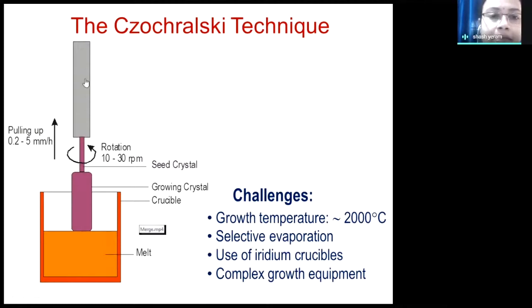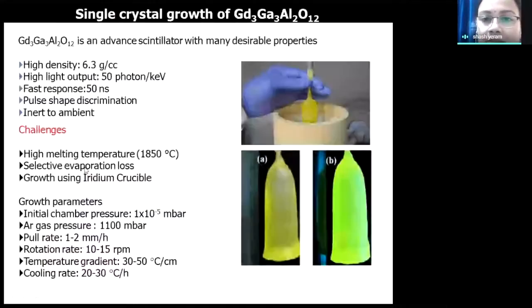And then the crystal seed comes and touches the melt, and very precisely, using rotation and translation, this is pulled upwards. So this is called the seed rod. The seed crystal comes and touches the melt, and then it is pulled upward, so that first the nucleation site is there at the seed, and then very slowly the crystal keeps on growing. So this is how the crystal grows; you see here the photograph.